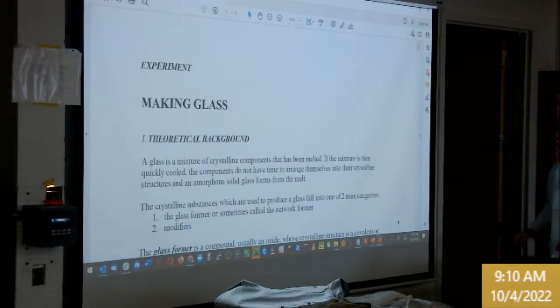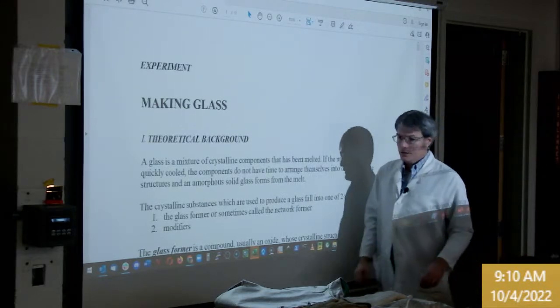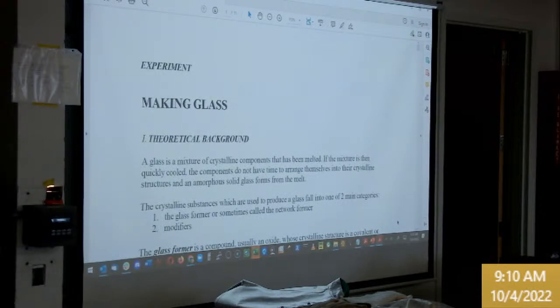Today we are making glass. The glass has been baking out here overnight, or incubating. So this is at 1150 degrees, so very warm. I'm going to go ahead and bump this up a little bit so that while we're talking we can get an extra 50 degrees. We're going to cast this at around 1200 today.